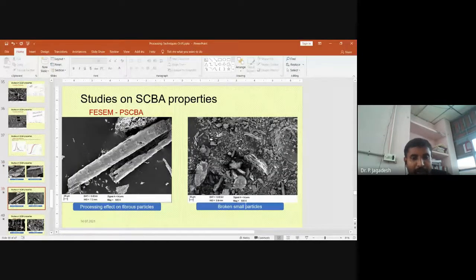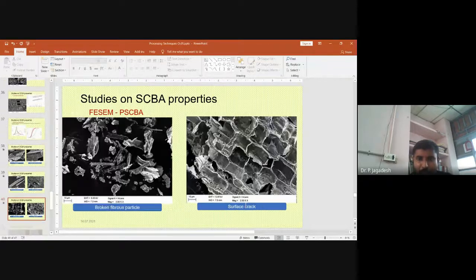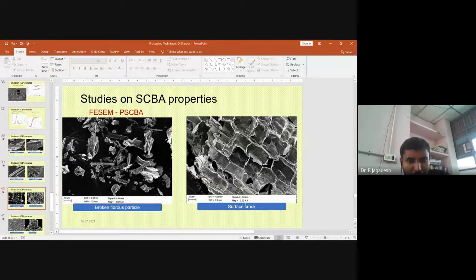You can see the processing effect, that is the impact of smaller particles on the fibrous particle. The broken particle sizes are shown here, and more amount of smaller particle sizes are formed. Even fibrous particles are broken into smaller pieces, which increases the surface area inside your processed sugarcane bagasse material. There is also surface crack in fibrous material with the formation of nanopores observed.